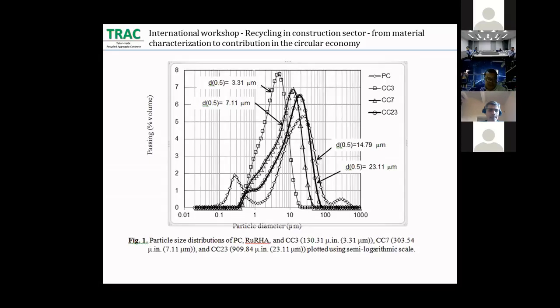It could be observed that the most common particle size of CC, in the range of 0.5 to 10 micrometers, is at the lower limit of the Portland cement particle size, indicating that the calcium carbonate can potentially fill the volume between the PC particles. When calculating using the median particle size, D50, which refers to the diameter at which 50% of the distribution is above, it can be determined that the smallest CC is CC3.